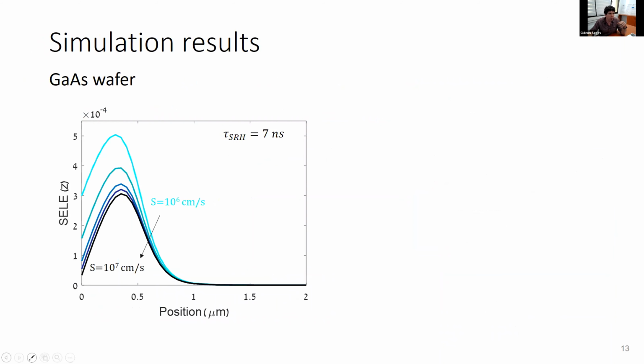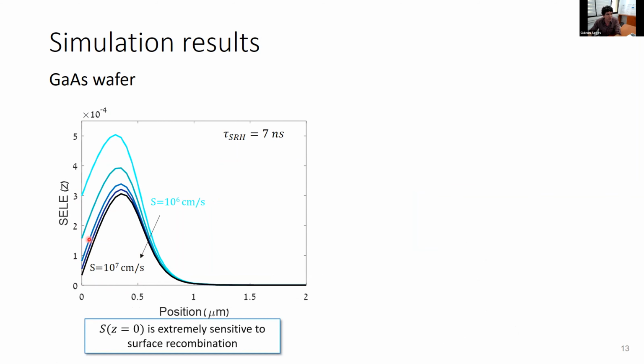These are SELE profiles with the surface here at Z equals 0. And as it follows pretty much the same shape you've seen earlier, as N1, and as one would expect, we see that the SELE at the surface is very sensitive to surface recombination. Each of these profiles is for a different surface recombination velocity, if I haven't said so earlier.